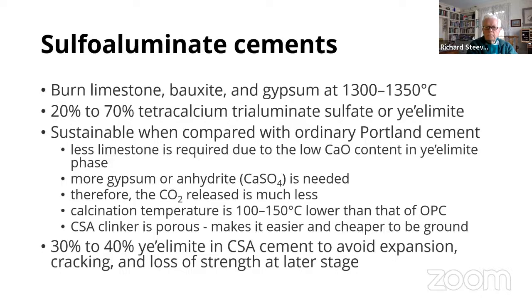So sulfo-aluminate cements: you burn limestone, calcium carbonate, bauxite, which is what contains the aluminum, and gypsum at roughly 1300 degrees centigrade, and you get this 20 to 70% of tetracalcium trialuminate sulfate. You use less limestone when you do this, and because of that, you produce a little bit less carbon dioxide. You use more gypsum, which is that calcium sulfate, and you end up with something that is a little bit more porous.